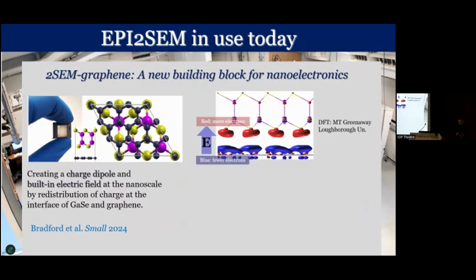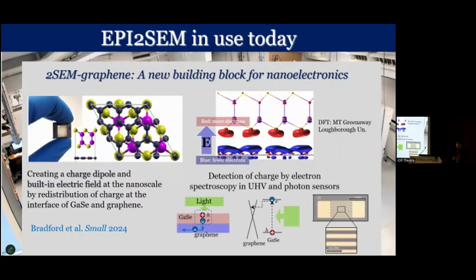What is interesting is that we can then start engineering the electric field at the nanoscale. For example, as you bring one layer next to each other, there is a charge redistribution at the interface. So for example, one layer becomes more negative than the other. And so this corresponds to an electric field that can be quite significant, a few hundred meV over a length scale of few angstrom. And so we can use this built-in electric field to realize photosensors, where this built-in electric field is used to separate, for example, photocharges, electron and hole generated by light.